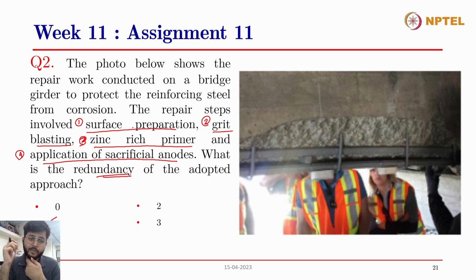It is not a corrosion protection system yet. But the third one, application of a zinc rich primer, is a corrosion protection system. When you apply a zinc rich primer on a concrete surface, it will act as a sacrificial anodic protection, or a galvanic protection system. So applying a zinc primer will provide a sacrificial anodic protection system, because the zinc present in this primer coat will get corroded while protecting the rebar inside the concrete structure, as we have also discussed in the previous sessions.